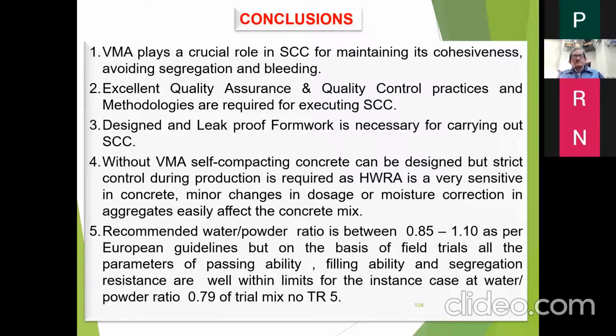And these are the conclusions. VMA plays a crucial role, as I have been telling, for maintaining cohesiveness and avoiding segregation. Excellent quality control and good construction practices are required. Well-designed and leak-proof formwork is necessary. Without VMA, self-compacting concrete can be designed, but strict control during production is required, as HRWA is very sensitive in concrete. Minor changes in doses or moisture correction will easily affect the concrete mix.